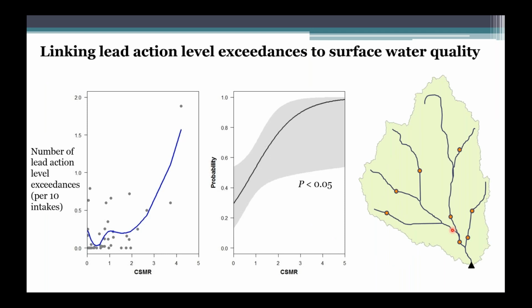Okay, so we looked at the number of action level exceedances compared to chloride concentration, Larson ratio, and the chloride to sulfate mass ratio. And here we're looking at the site average chloride to sulfate mass ratio on the x-axis versus the number of action level exceedances on the y-axis. Okay, and it's pretty messy, but there is a tendency to have a greater number of exceedances at high chloride to sulfate mass ratio. One thing that makes the figure really difficult to look at and to analyze statistically is the number of sites that had 0 action level exceedances. Okay, and the presence of these occurrences make the data difficult to analyze using traditional means.